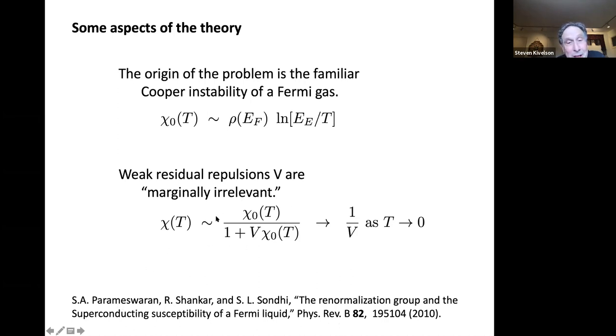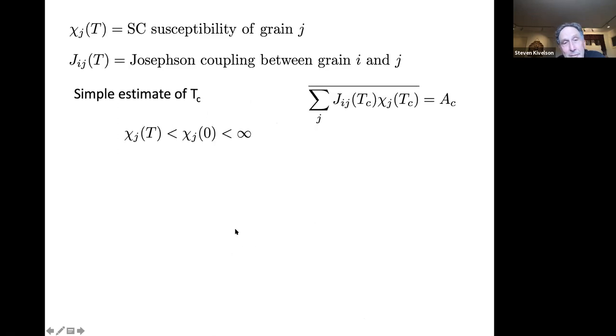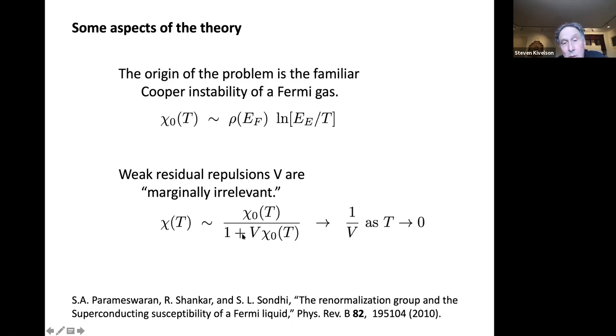And so the RG, the perturbative RG, is actually no different from summing ladder diagrams. It gives you an RPA-like expression for the susceptibility. And now if V is negative, this of course has a pole, which is the BCS transition temperature. But if V is positive, this has no pole, but this repulsive V changes us from having a susceptibility that diverges at zero temperature to one that approaches a large but finite value as the temperature goes to zero. So in the presence of repulsive interactions, we've qualitatively changed the answer to the problem. No longer are we perturbatively unstable to superconductivity, we have some range in which we're stable to superconductivity.